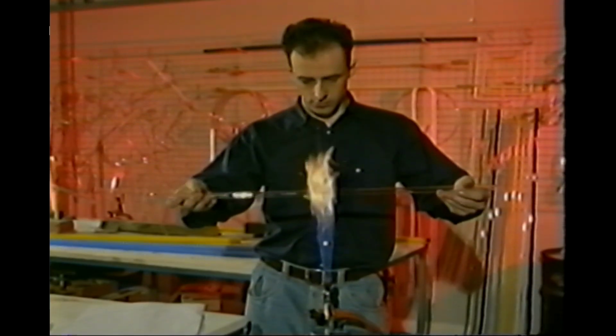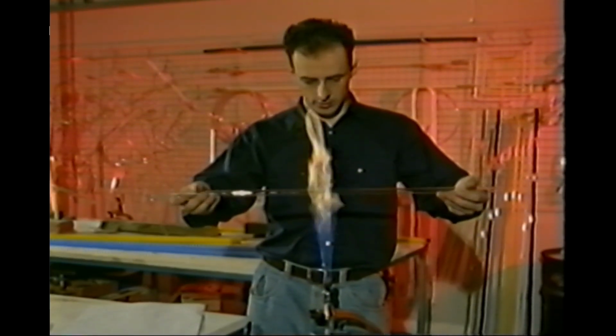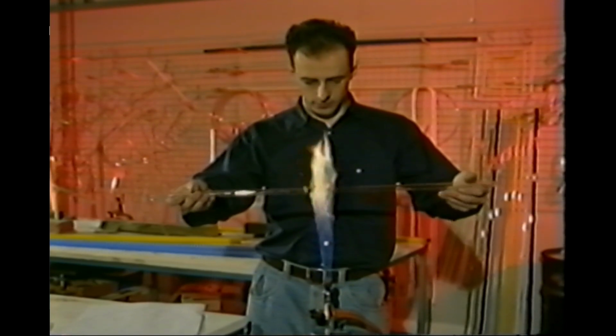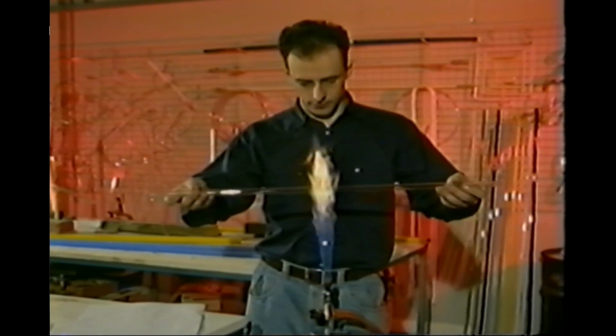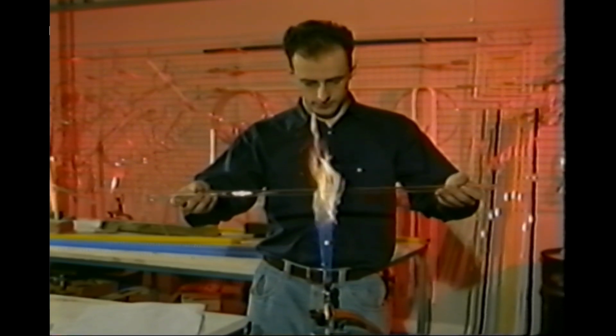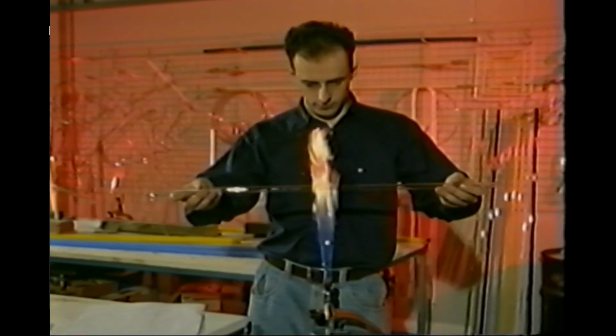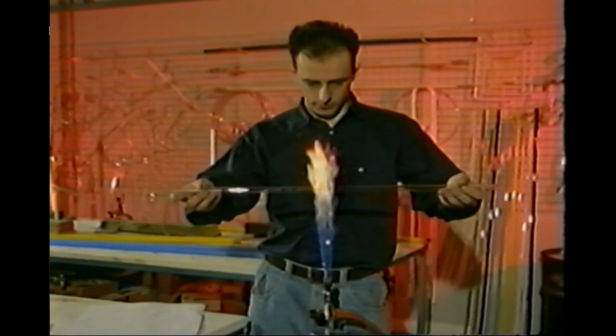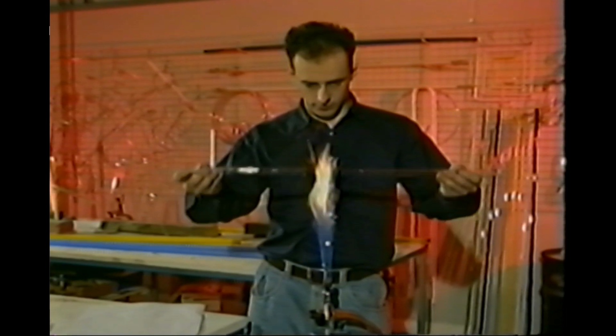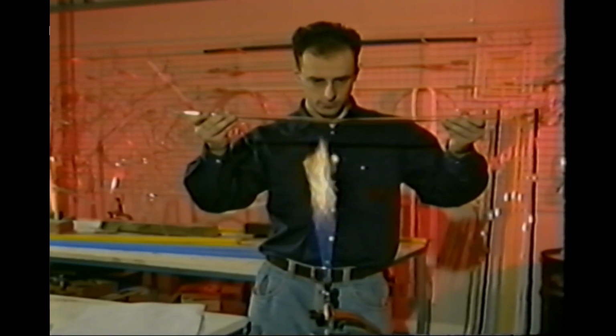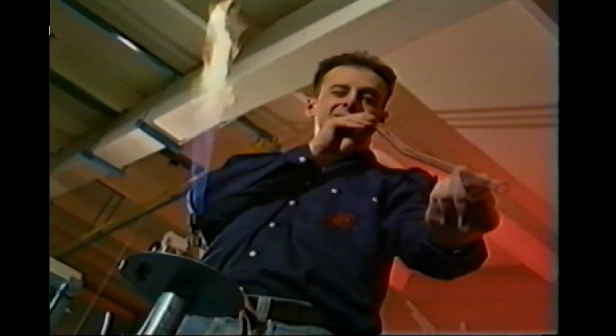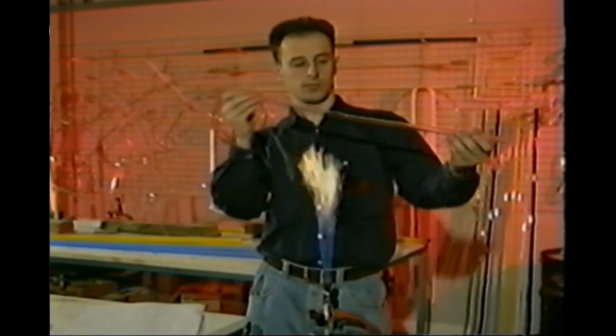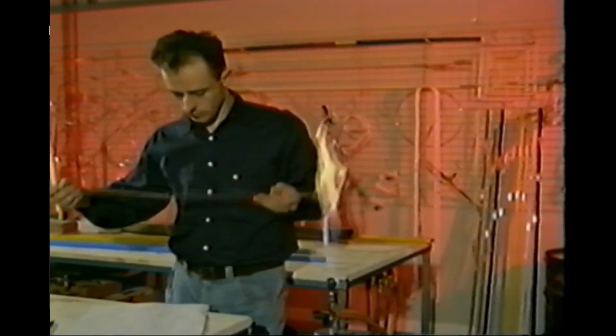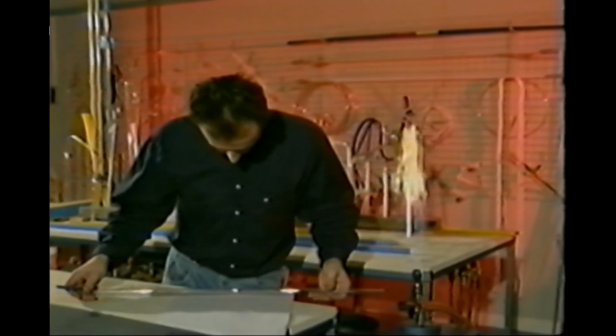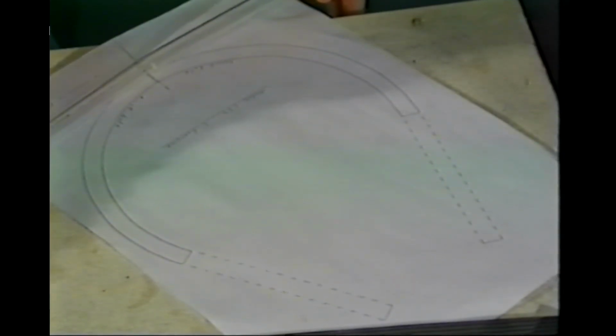For the first bend, roll the glass forwards with all the fingers and thumbs of both hands, with the hand positions far enough towards each end of the tube to ensure good balance. When the heated area softens, stop rotation. Raise the tube to head height and move the right side arm upwards to create a small bend at the mark position. With the pencil, mark the tube to the right of the first bend, approximately 10 to 12 millimeters along.